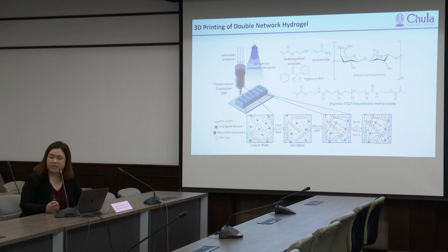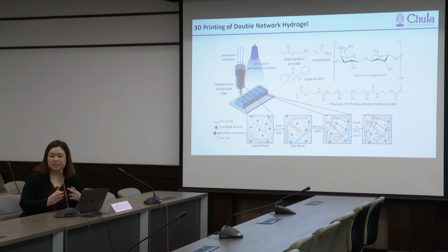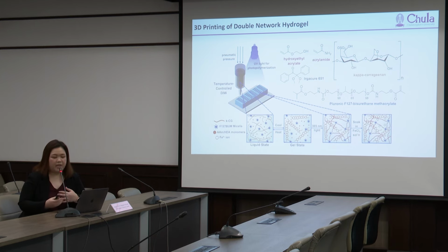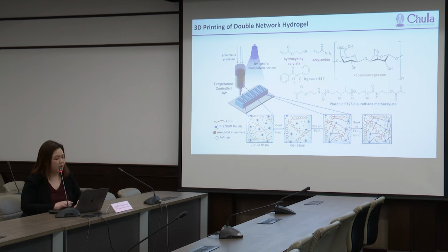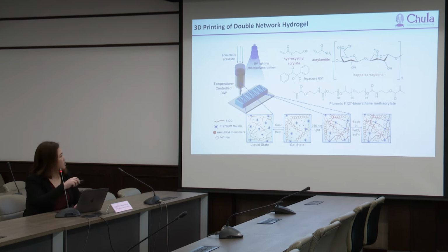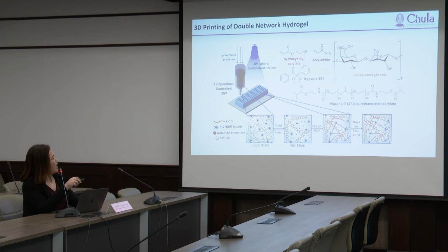So in this project, we aim to use 3D printing technology to print a conductive wearable sensor, using kappa carrageenan as the main material. In this case, we also add hydroxyethyl acrylate and acrylamide as co-monomers. We also add Pluronic F127 bisurethane methacrylate as a cross-linker. We also add the photoinitiator in here to initiate the polymerization.